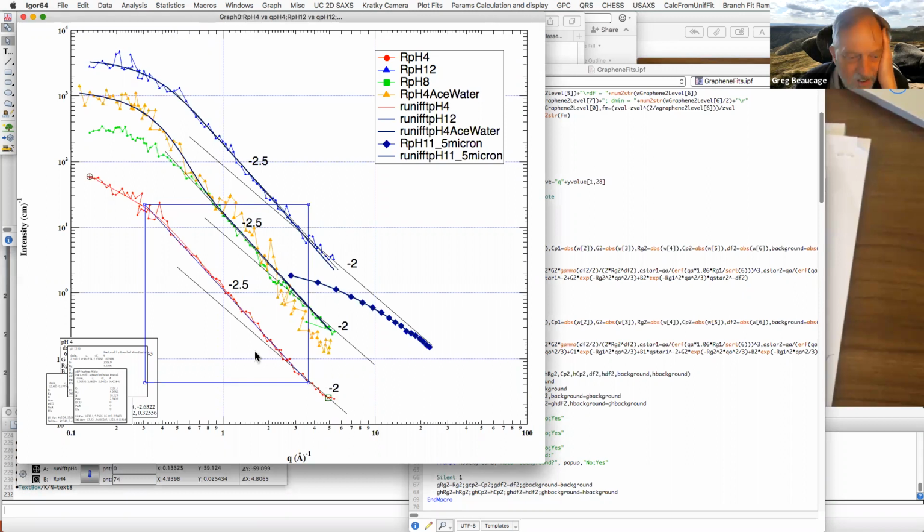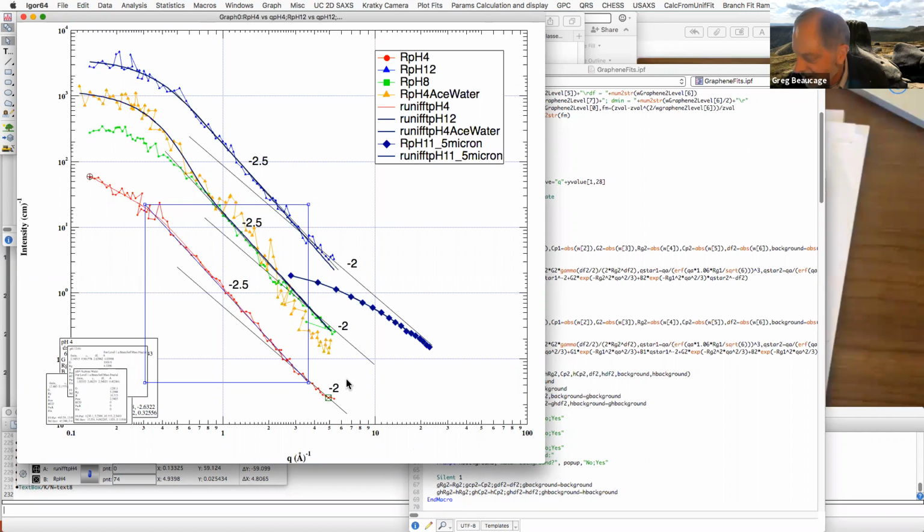So this is pretty reminiscent of a polymer where you have a persistence length, right? You would have power 1 for a polymer because it's got a rod persistence. In this case, it's power 2 because you have a sheet persistence. So locally, at some extent, it's got these alkene bonds, right, that are planar, and they're conjugated. So somehow it's going to go off and be planar. Everything's planar linked to planar. It's planar, right? So this will also be planar. So the whole structure is planar as long as it's got conjugation,